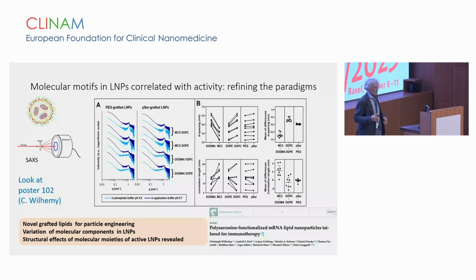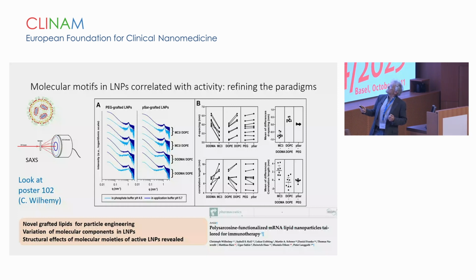And one approach is to get understanding of the systems, to investigate them and to reveal certain coherencies in that. And here structure is one parameter which is of course very important. What you see here is an extract from an LNP work where we did small angle X-ray scattering and investigated systematically variations of certain cationic lipids and helper lipids, and found that there were some interesting counterintuitive observations on correlating structure and activity. This is plotted here. I can't explain it, but if you're interested, look at it.